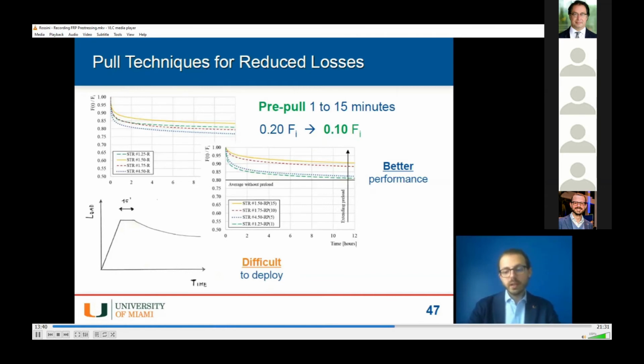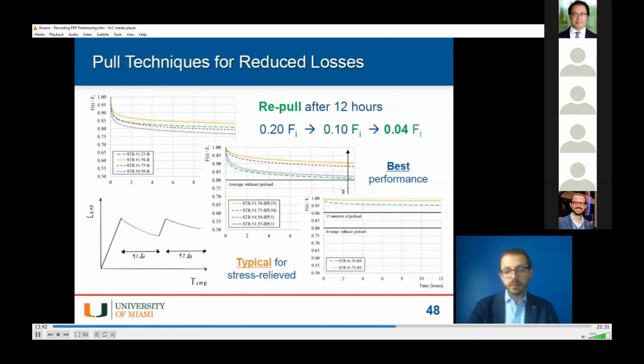So we propose an alternative procedure: pulling our strand up to the level that we want, letting it rest overnight for at least 12 hours, going back to the field, and pulling it again. At this time, we pour our concrete, and then we let it rest for 12 hours for the concrete to harden, before we release our strand and transfer pre-stress to our structure. This proved to be the most effective solution, and even though it's quite time-consuming, it's something that a lot of precasters are still familiar with, because it used to be standard procedure before low-relaxation strands